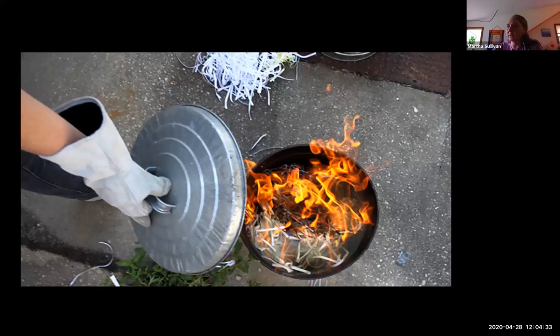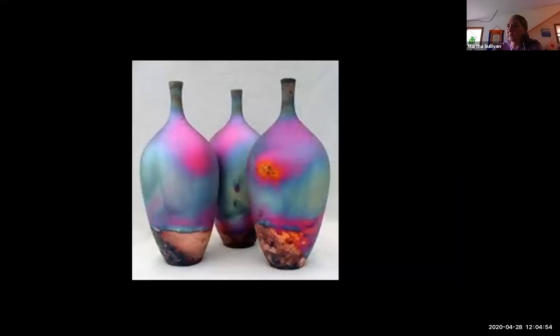And when it's still hungry and it still wants to burn, it starts to pull the oxygen out of the glazes itself, literally pulling oxygen molecules out of the glazes. And when you do that, you change the chemistry and then you change the color. So that is called reduction. It is a reduction of oxygen in an environment, and that changes the glazes. And it's variable. It's hard to control. But here for these, it's giving these really wild spot colors.